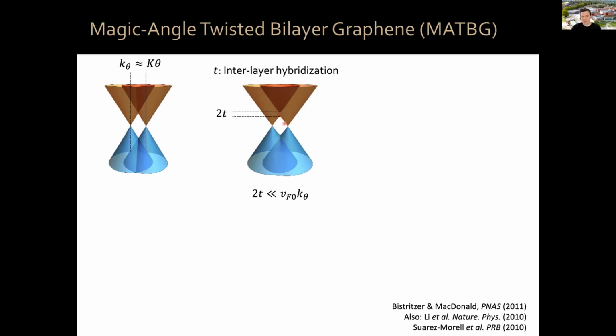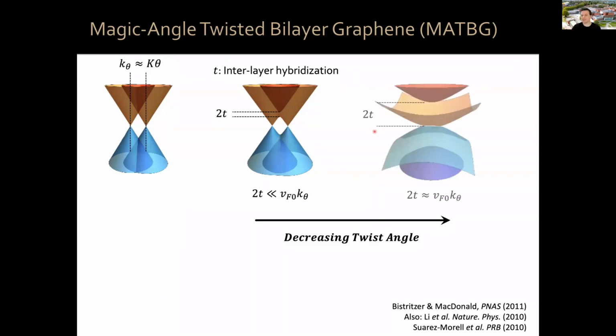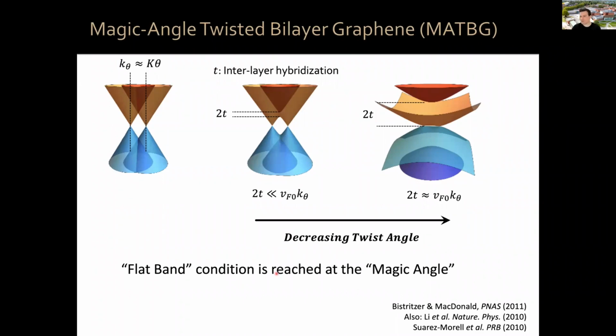Now this is the situation where the interlayer hybridization is small compared to the absolute value of this crossing point. As you now decrease the twist angle, this band gets pushed down to lower and lower energies until it reaches 0. That is the situation where we say that the flat band condition has been reached, and in graphene it is reached at the magic angle. This magic angle for graphene on top of graphene is 1.1 degrees, and this term magic angle was coined by Bistritzer and MacDonald.